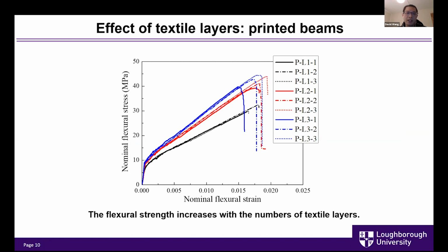And also we studied how the textile layers will affect the flexural behavior of the printed concrete beam. As we can see from this, if we increase the layers of the textiles, the flexural performance is improved. The improvement from 1 layer to 2 layers is significant, but the difference between 2 layers and 3 layers is less significant. The reason is because of the location of the different layers of textiles.